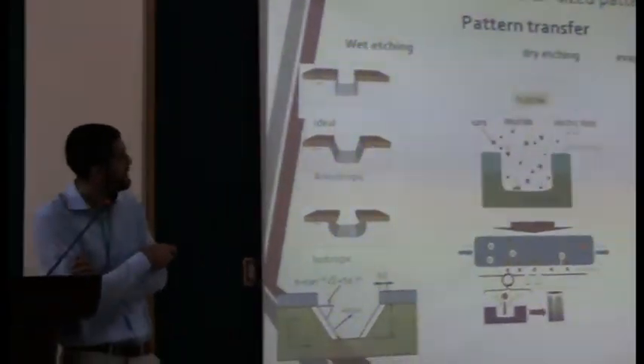So we can distinguish in wet etching when you are doing the process in a solution. In particular, we can distinguish between isotropic and anisotropic etching, and dry etching when we are exploiting the use of plasma to selectively remove the exposed part of your sample to replicate the structure here. Or when you are using adding techniques, such as deposition of particular materials that can be exploited for etching, or you do the etching and then deposition. So you can combine in infinite ways the techniques that are available in order to obtain the sample.